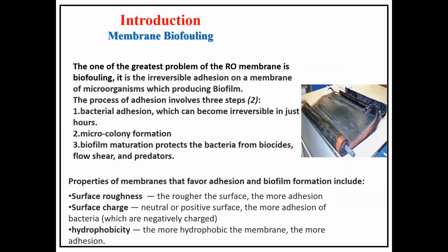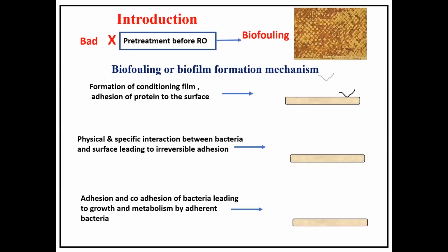What membrane surface properties favor adhesion of these bacteria or biofilm? When the surface of the membrane is rough, it favors the adhesion of bacteria. Surface charge: a neutral or positive surface also means more adhesion of bacteria, since these bacteria are mostly negatively charged. Hydrophobicity: the more hydrophobic the membrane, the more adhesion. But with inadequate pre-treatment before the RO, biofouling can appear.